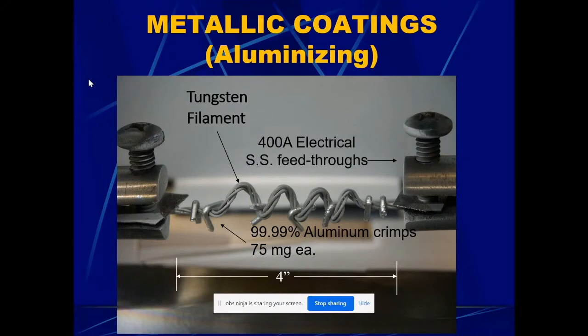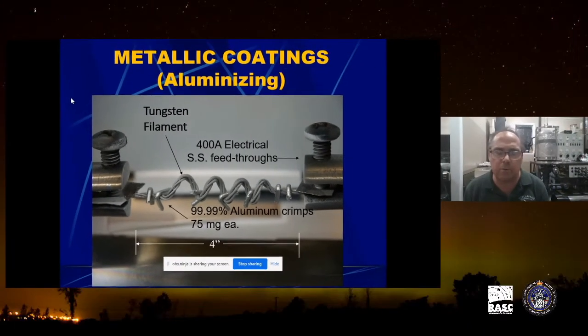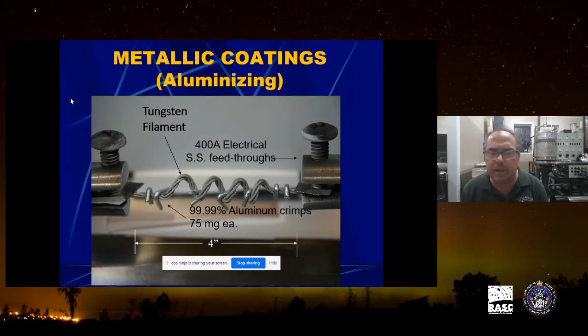What happens is the aluminum will melt at 600 degrees Celsius, and then it'll start getting hotter and hotter. At about 1200 degrees Celsius, it'll actually boil off because it's in a vacuum. So it'll turn into a vapor, and the vapor will go in all different directions. A very, very thin coating will deposit and condense on the glass substrate, no more than 600 atoms thick, which is about 1,000 times thinner than saran wrap. So it's a very, very thin coating.